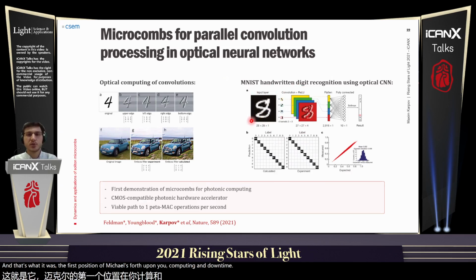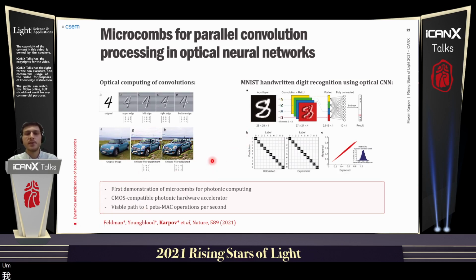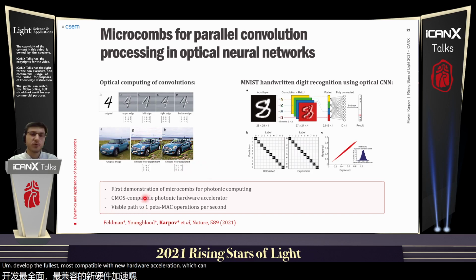And we also demonstrated that by combining silicon nitride technologies with phase change materials, we can develop fully CMOS-compatible photonic hardware accelerators, which can access a really high number of multiply-accumulate operations per second.